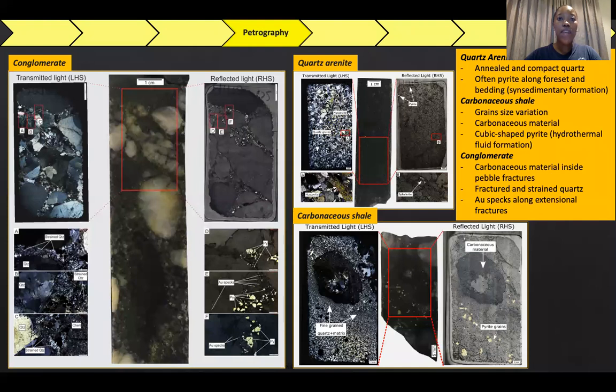Petrographic analysis was made in these units, and the quartz arenite samples show annealed and compacted quartz grains, and often the pyrite grains are orientated along bedding and cross-bed foresets. And this is indicative of syn-sedimentary formation. The carbonaceous shales usually have very fine-grained quartz. Specifically in the sample, there is grain size variation and fracture-filling carbonaceous material. The cubic pyrite grains are also observed, which is indicative of a hydrothermal fluid formation.